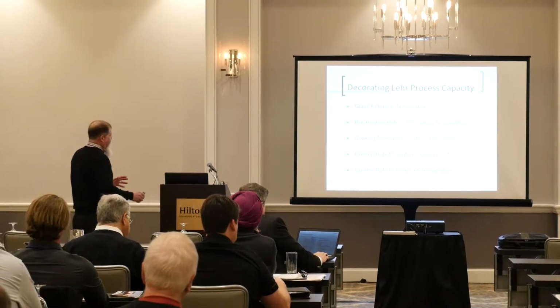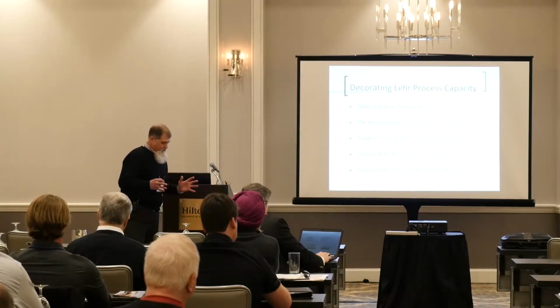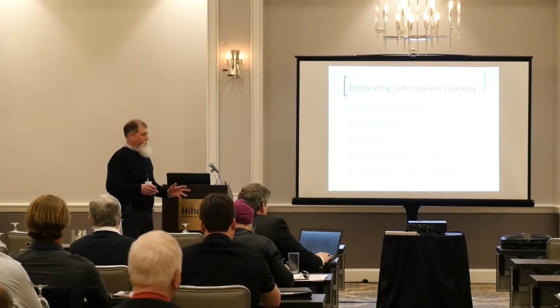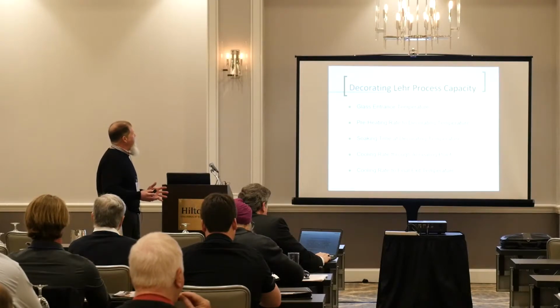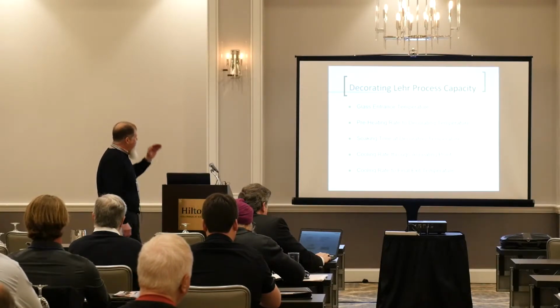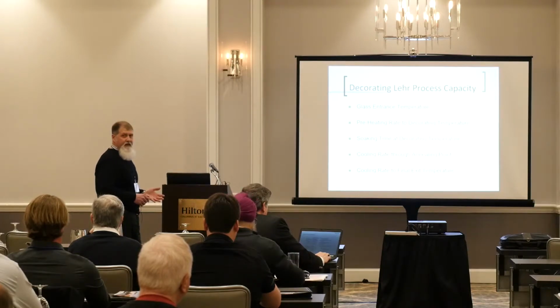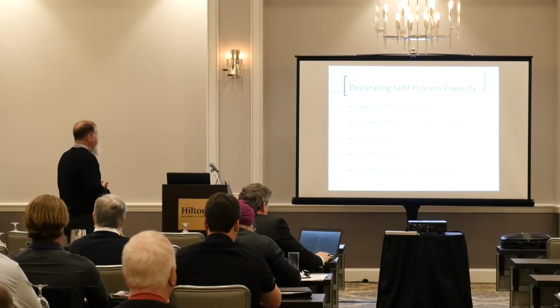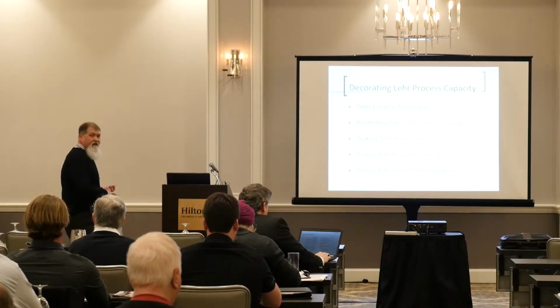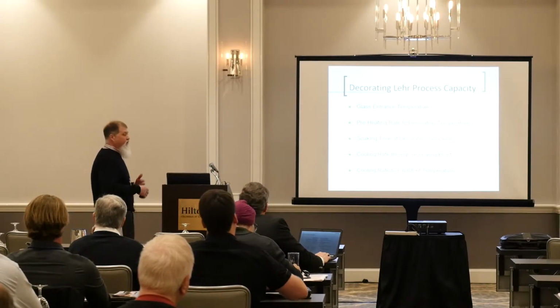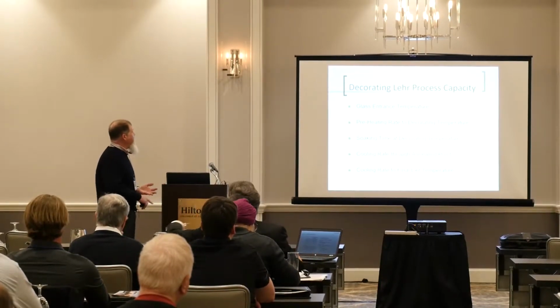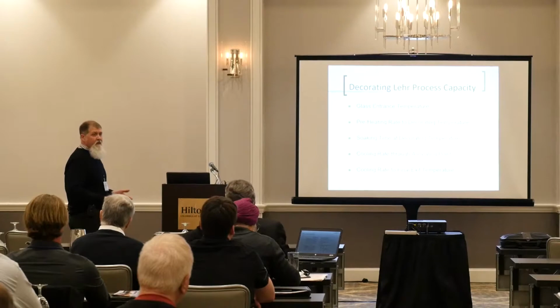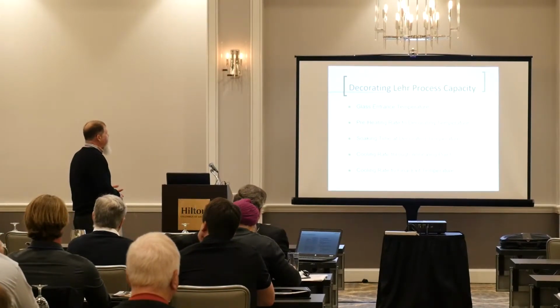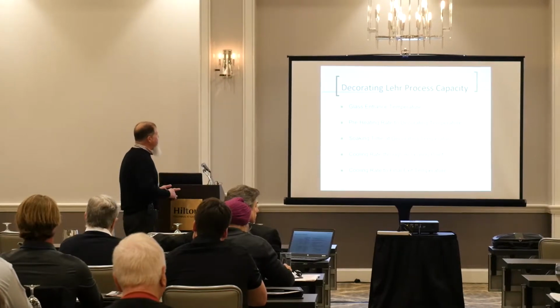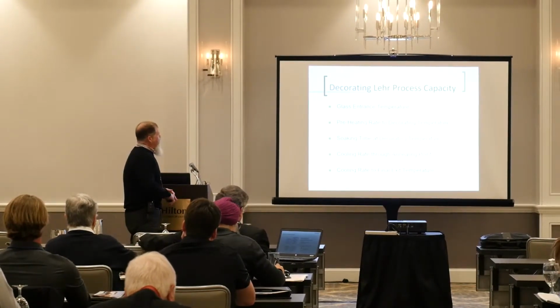Okay, so again, just trying to break down the basic elements of understanding the Lehr process capacity. So all of this is going to come into play. All right, your glass entrance temperature, the rate at which you're going to preheat the glass to your firing temperature. Obviously, the soaking time. All right, how long do you need to maintain the temperature to get the fire that you're looking for, get the finish that you're looking for? Cooling rates through the annealing point.